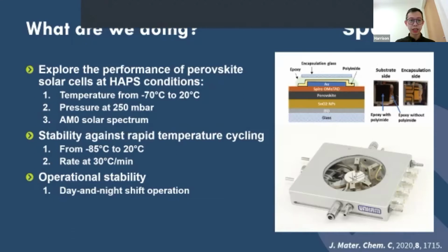And other than that, we also test the stability against rapid temperature cycling from -85 degrees to 20 degrees with a ramping rate of 30 degrees per minute. So it warms up and cools down quickly to test the mechanical stability, like thermal expansion, during the rapid temperature change. Also, finally, we test some operational stability by making some day and night shift operation.